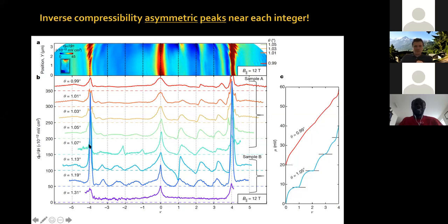Now, what you see here, let's focus, for example, on this 1.07 degree trace, this turquoise trace, or the one above or below. Starting from charge neutrality, you have this peak with a 1 over square root of density type decay of your inverse compressibility, your dμ/dn. Then we reach filling factor 1, one electron per moiré unit cell, and then there is a reset up with a decay again. And then we reach near filling factor 2, and you go up with a decay again. So you have these asymmetric peaks. Maybe it's easier to see the asymmetry in this 1.05 degrees or this 1.13 degrees trace, of these asymmetric peaks, which are a little bit like a sawtooth.